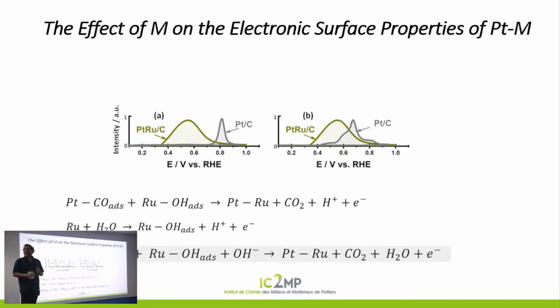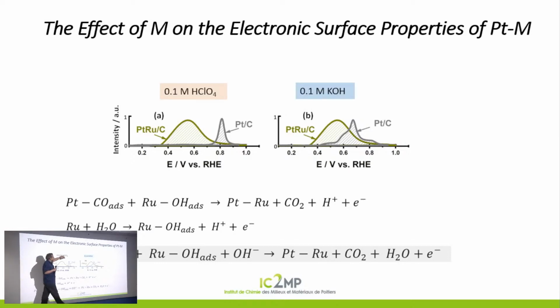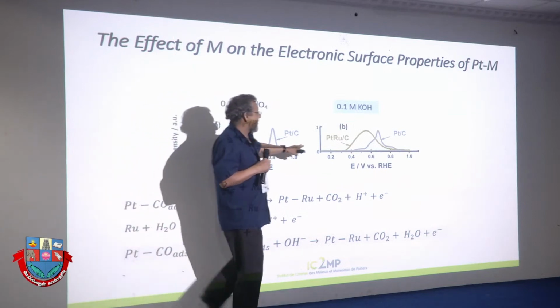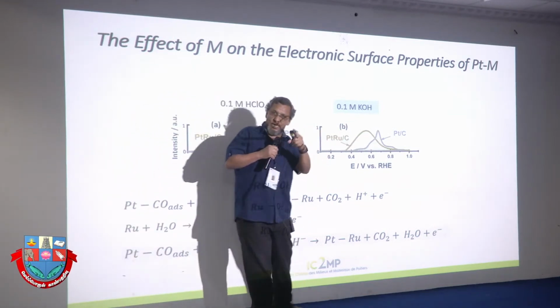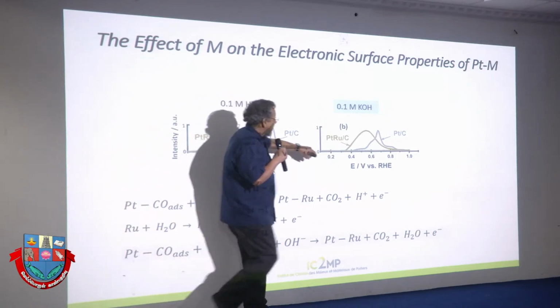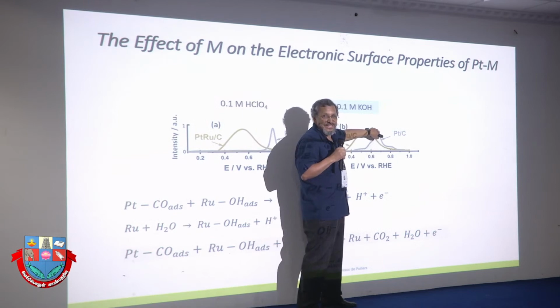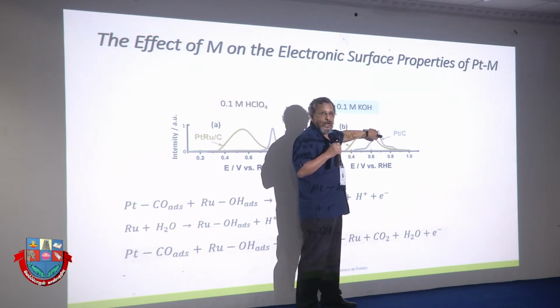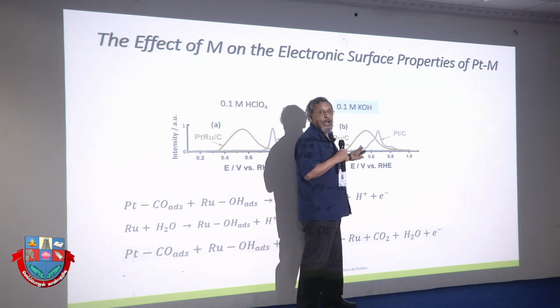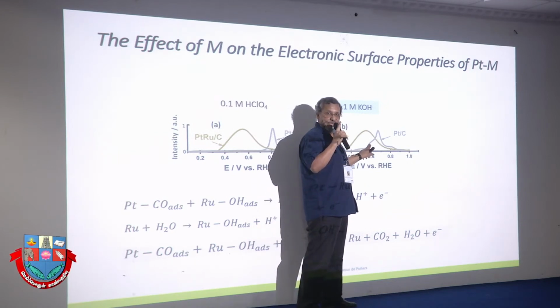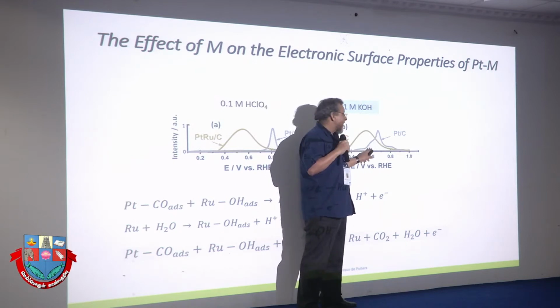I give you the answer. And now, which is very funny and interesting, when you have ruthenium or platinum, not core-shell, alloy at the surface, look what happened here when I have acid medium and alkaline medium. Actually, we observe the same curve, the green curve here, does not change for the alloy. But if you measure platinum alone, this is the answer for platinum. So platinum, in this domain, says that there is OH adsorbed that favors the oxidation of CO at rather low potential. That is what that result teaches us, okay?